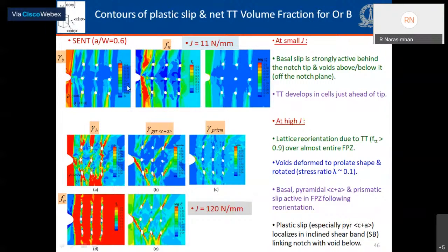So here, if you look at the plots for low energy release rate, the top set of images, initially basal slip and tensile twin volume fraction are evident from the top two images, taking place in the cells ahead of the notch tip. At large J, if you look at the bottom left image, those red-shaped contours in the FTT are complete reorientation of the lattice due to being engulfed by extension twins. Now, this triggers, as I noted from the unit cell, additional slip activity, like pyramidal C plus A.